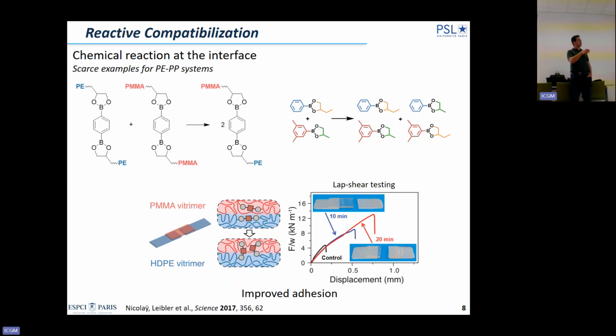So we take a PE which is cross-linked with these dynamic bonds. We take a PMMA which is cross-linked with the same bonds, and when we put them into contact, we can hope to create a chemical bond at the interface between PMMA and PE. And this was done qualitatively with a lap shear experiment, a bit similar to what I showed you. So HDPE was prepared, cross-linked with this bond. PMMA was prepared, cross-linked with this bond.